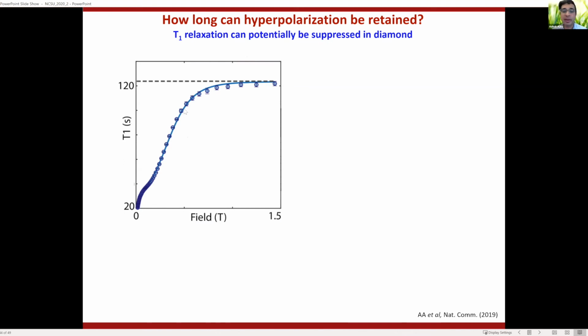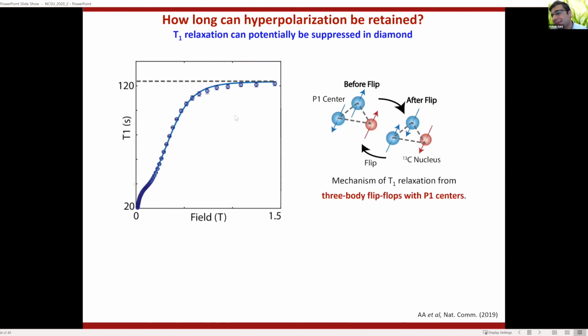So it turns out that we understand why this works. That's because the lattice contains other paramagnetics, which are not NV and which are called P1 centers. Alex Spinov knows all about them, but they are EPR active paramagnetics, which cannot be optically polarized. And it turns out that you can have a 3-spin flip process. Two P1 centers want to flip, and they're slightly energy mismatched. And to flip themselves, they flip a carbon. So if you're a carbon, you're a peaceful guy, but you see spin flipping randomly coming from the P1 centers. And this is what causes this mechanism.